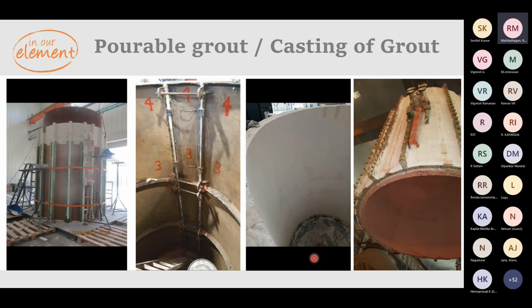So you can see these numbers, those are forms which can be removed after the setting. In this form, we normally give a small amount of vibration, and this vibration helps the castable to flow smoothly and to avoid any voids. Normally, this is done in large capacity crucibles, but we can do the same for the small capacity crucibles also. This gives a very smooth finish and has a better strength compared to trowelable castables.